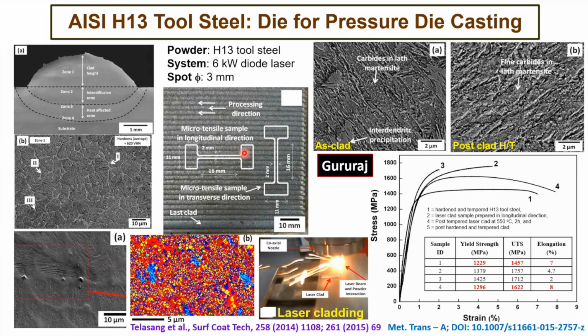And then scoop out tensile samples along the build direction or across the build direction. You see that their tensile curves are very similar, even better than the original H13 tool steel material. That's because you actually have very fine carbide, very fine martensite lath structure or needle structure, alongside very fine carbide distribution and formation in between the laths. Because of this fine grain structure and very uniform distribution of carbides, you tend to have a tensile property even better than the original H13 tool steel.